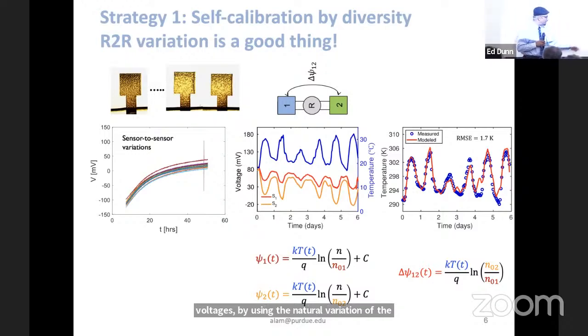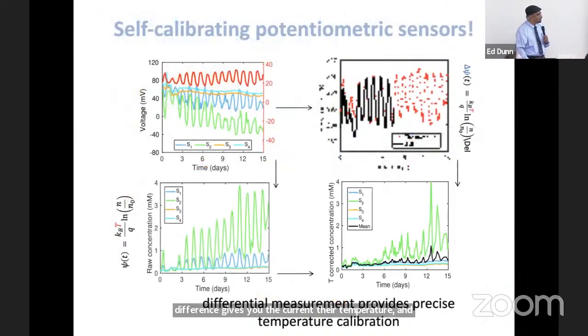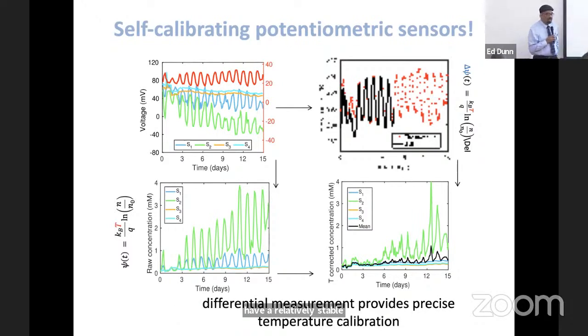So cheap is actually better, because this N01 and N02, so long as they are slightly different, the difference gives you the current, the temperature. And once you have the temperature, you have all these fluctuating, seemingly random things, this blue, green, and red, everything fluctuating. But as soon as you subtract, you find out that it is measuring the underlying temperature fluctuation during the morning to the afternoon. And once you correct it, all those fluctuations essentially go away, and you have a relatively stable signal. And this then allows you to get precise measurement without having to think about temperature.